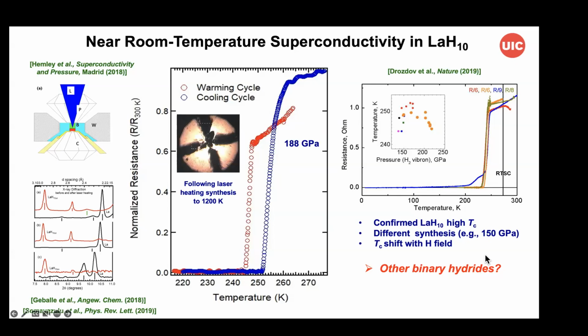You can see that from the clear X-ray diffraction. It was in remarkable agreement, slightly lower pressure than the predicted calculations, but essentially very good agreement with the stability range that was predicted theoretically. And then we followed up with measurements of the conductivity, much more difficult than typical experiments because we had to do the laser heating in combination with the probes and this very small sample at pressures approaching 200 GPa, and ensuring that we transformed the sample under pressure without any chemical reactions with electrodes and other parts of the cell. We saw this remarkable conductivity onset beginning as high as 260 Kelvin at these pressures of sort of 180 to 190 GPa.